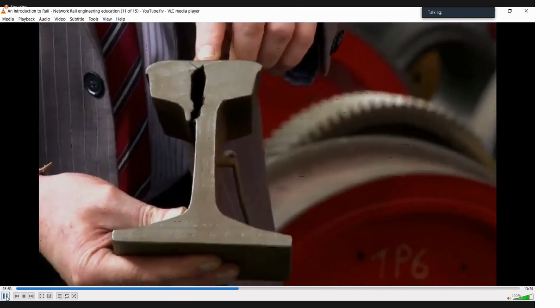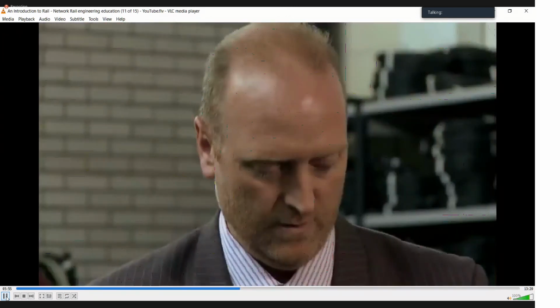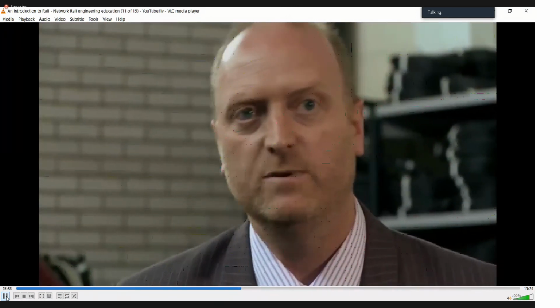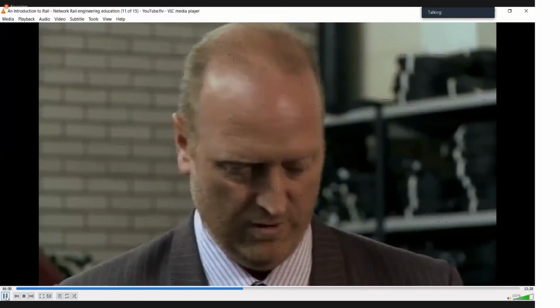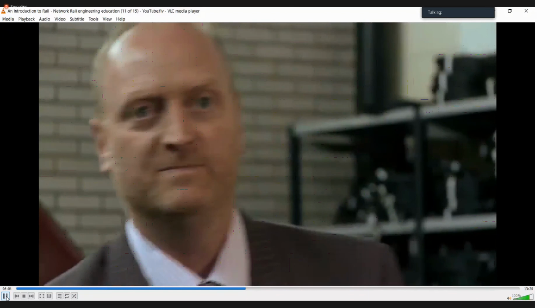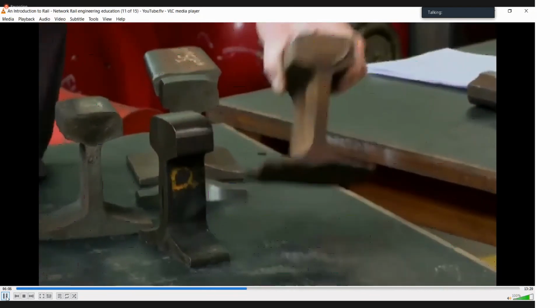Most of our defects of this type occur in older rails where there are either inclusions or impurities within the rail steel which form a point of weakness which under repeated loading will cause the rail to fail. Another type of degradation is corrosion.